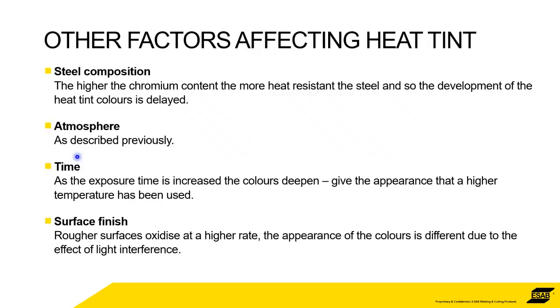So obviously, heat tint is affected by a number of factors, several of which are listed here. Obviously, steel composition. The higher the chromium content, generally, the more heat resistant the steel is, and so the heat tint colours are delayed. It sounds quite contrary, really, that you've got more chrome in the base metal and you're going to get less heat tint. But it's really the more chromium in there, the more heat resistant the steel is. So the colours become delayed.